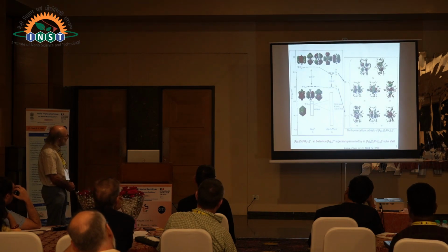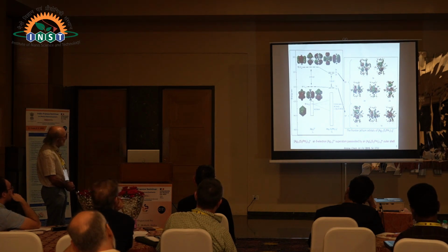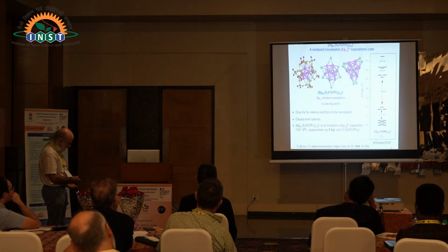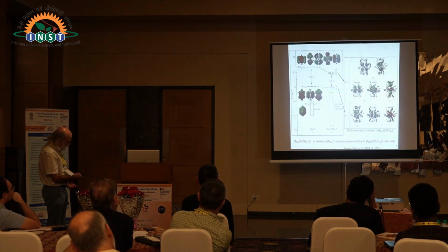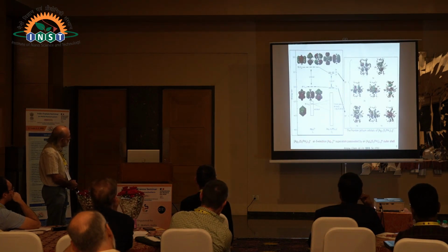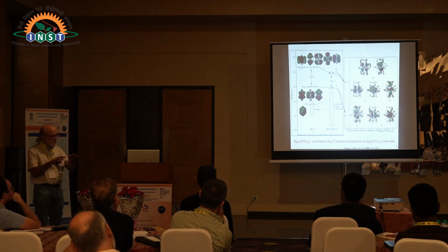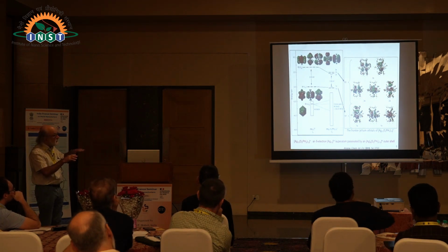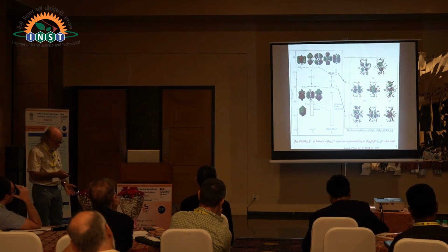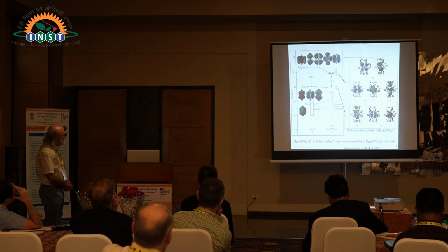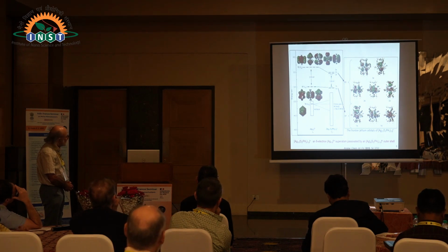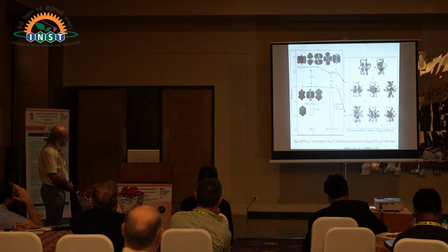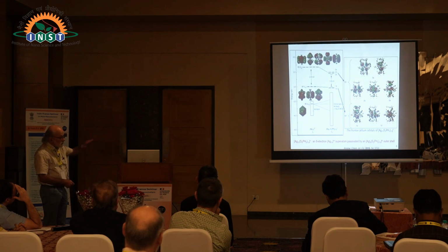We can go a little bit further on the structure. This is the electronic structure of the core, silver 13 5+, in icosahedral symmetry. This is the D band, which is roughly non-bonding, but we have also the 1s orbital, which looks like the 1s orbital of an atom, but this time it's expanded over the whole sphere of the cluster. The HOMO is triply degenerate, and this is a 1p HOMO. You see py, px, pz, and the LUMOs are the 1D LUMOs, which are there.